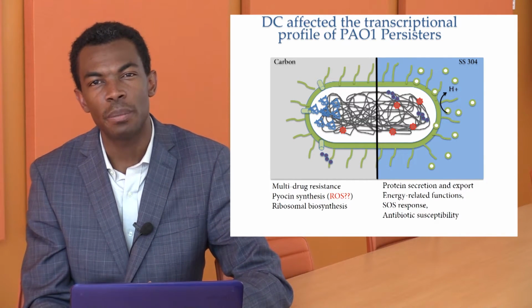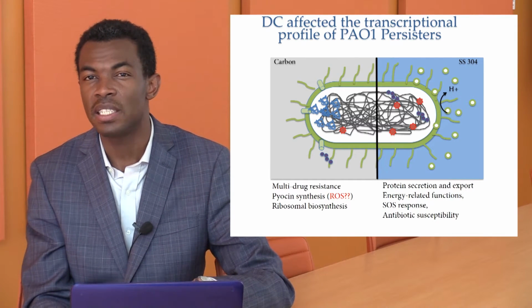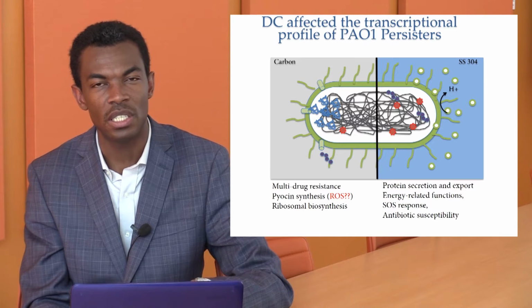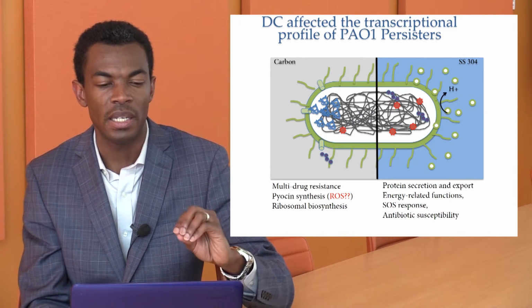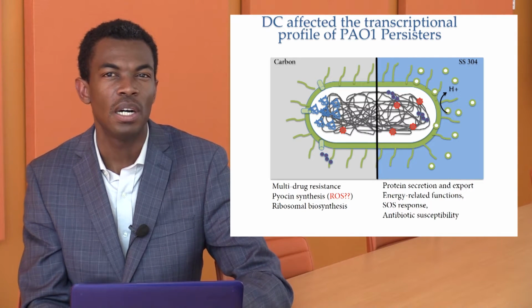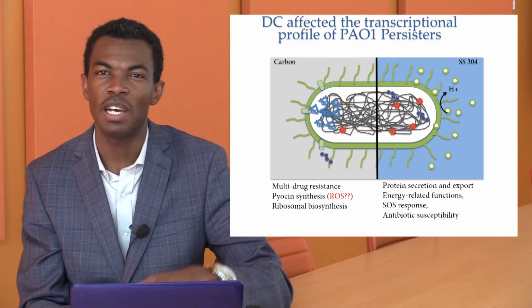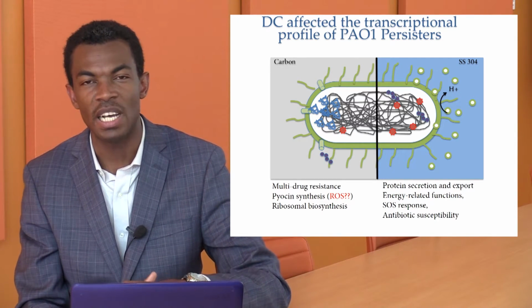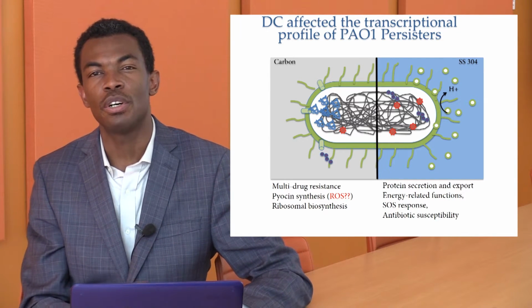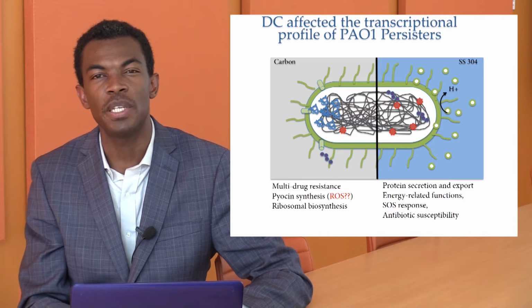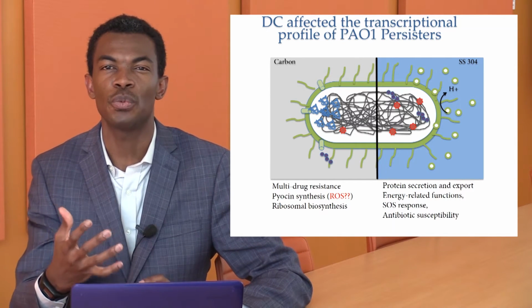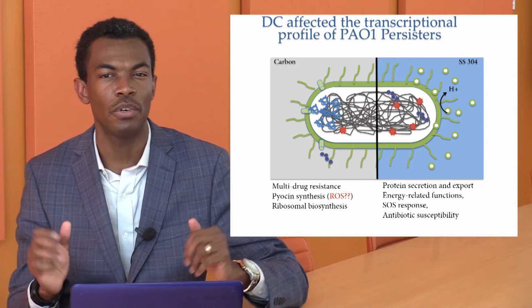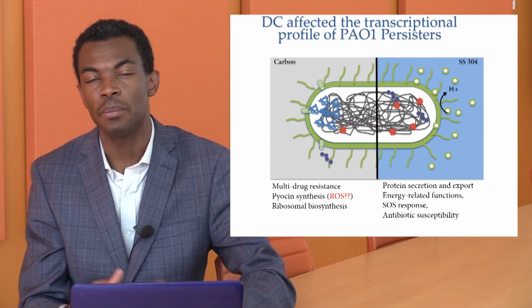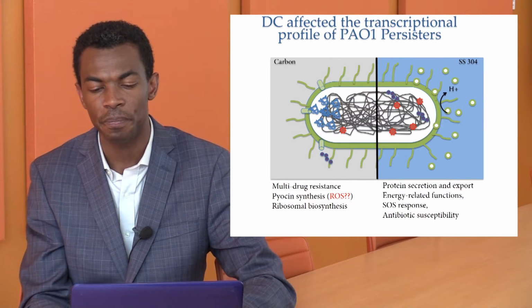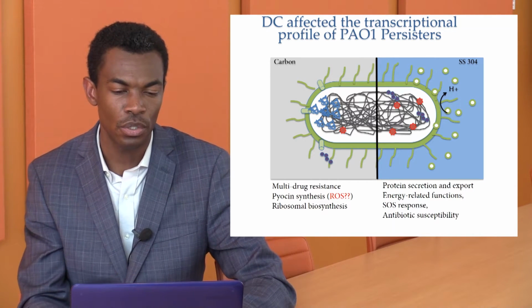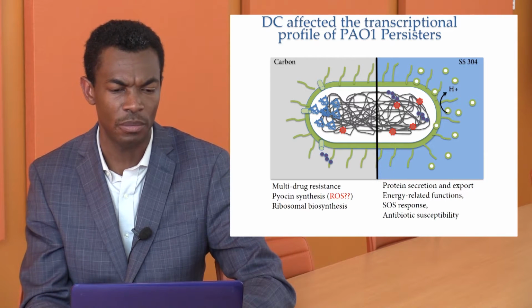So during the carbon treatment, among the proteins that seem to be accumulated inside the cells are those pyocin related genes. Pseudomonas has 18 of them. In this treatment, there were 17 of those genes that were highly induced, showing that the treatment was affecting mostly the cells under this aspect. Previous studies have linked the expression of pyocin related genes as being also a way for the cells to respond whenever they're exposed to some type of ROS, reactive oxygen species. So in this case, we can see that maybe our carbon treatment generates some type of reactive oxygen species that lead to the secretion of pyocin related genes.